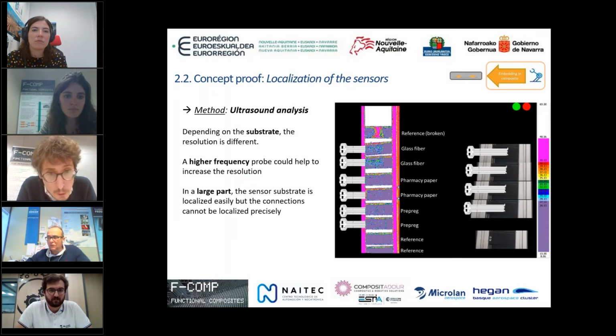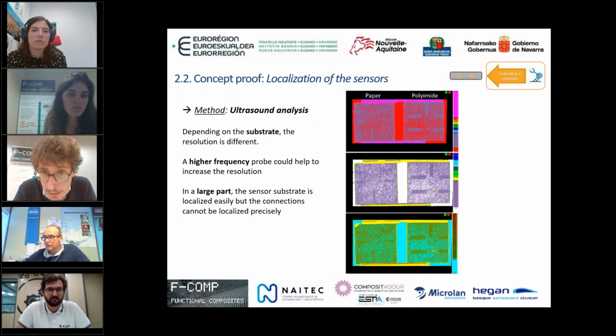One of the other points that we check is trying to verify where the sensors are, so that we can machine later until getting this sensor out. We see in the photo on the right that depending on what the substrate is, the image obtained in the ultrasound analysis is different. And this test is done by COMPOSITADOUR. They use a 10 megahertz probe. The conclusion is that maybe using a higher frequency probe, we will get better results. But this is something that will be done in the future. Another point you can see in the next photo is that if the sample is larger, it's easier to detect where the sensor is. You can see 5 sensors inside each of the laminates in the image, and as well, depending on the material of the sensor, it is easier or not to detect it.